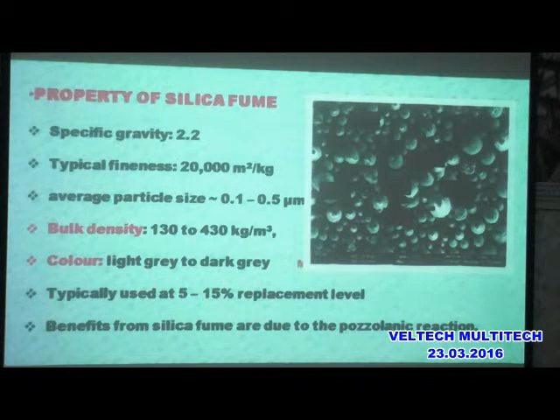The properties of the silica fume. The specific gravity is about 2.2. The fineness is 20,000 meters square per kg. Average particle size is 0.1 to 0.5 micrometer. Then its bulk density. The unit weight of the concrete is 20 kilonewton per meter cube, whereas the bulk density of this silica fume is 13 kilonewton per meter cube to 43 kilonewton per meter cube. Then the color is light grey to dark grey.